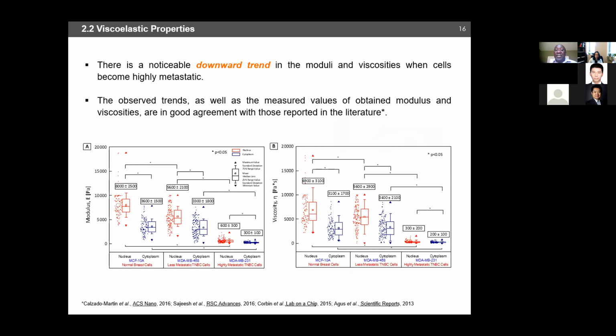So when you look at the elastic properties, the Young's moduli, for cells at different stages of metastasis, what you find is that the initial cells, which are non-tumorigenic cells, have high modulus. But as you go to the less metastatic cells, your modulus ranges reduce. And then as you go to the highly metastatic cells, you get even lower moduli.